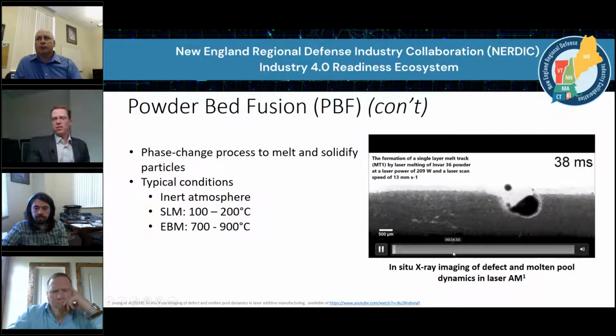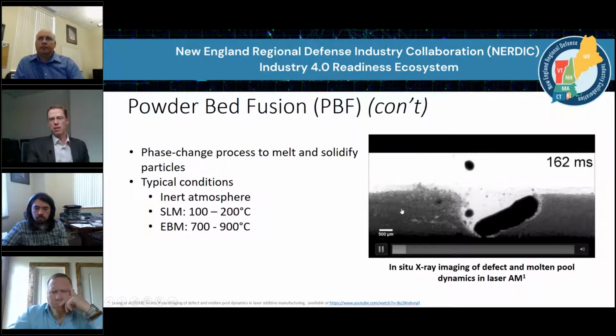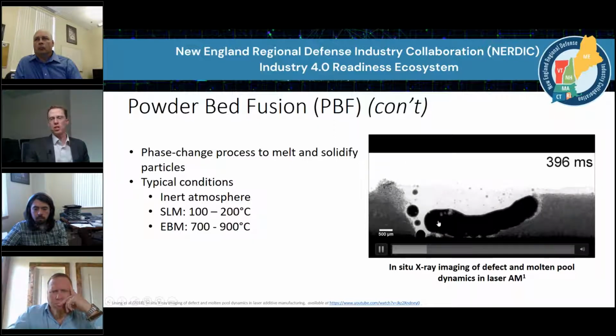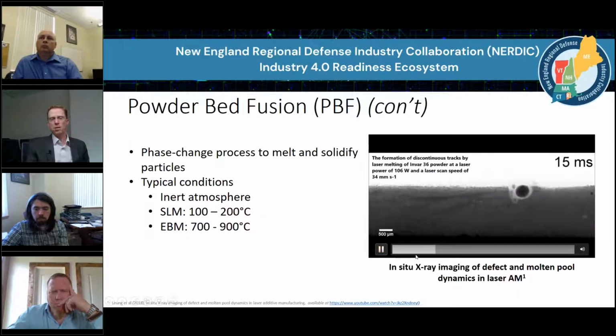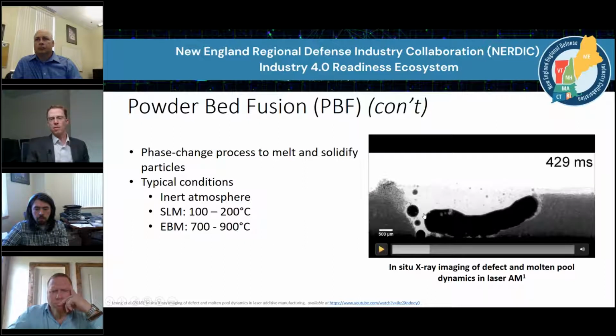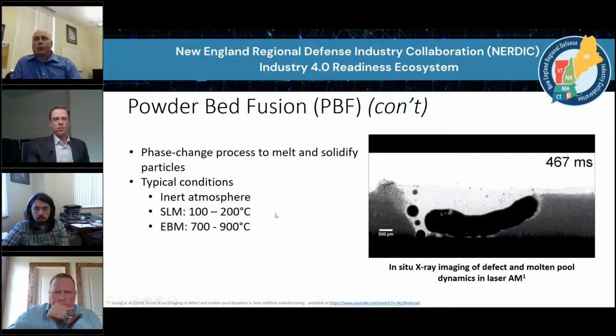What I want to look at next is an SEM image that shows this process of solidification. What we have is a powder bed shown here with all the powder. As the electromagnetic source passes over, you get solidification. And you'll notice that at the macro scale, pretty much here's a solid taking place. I'll pause it right there. You can end up having some pores that form. Here this dark black is a solid, this circle black here is a pore, but then we have space between, which is a void or some sort of pore structure that's forming. That's an important consideration with powder bed fusion.